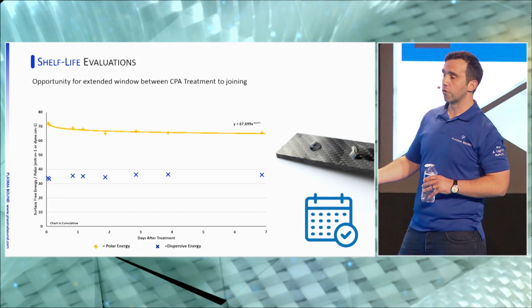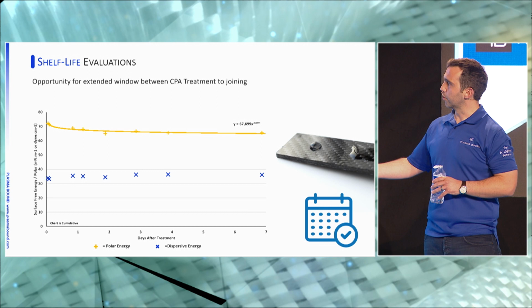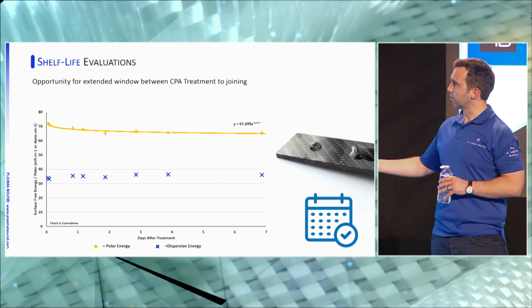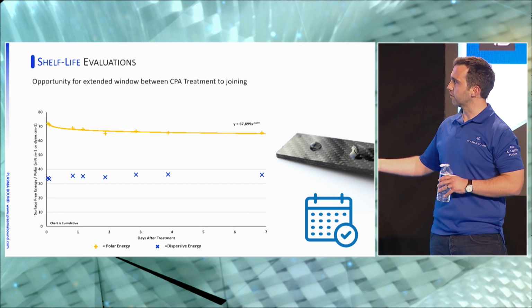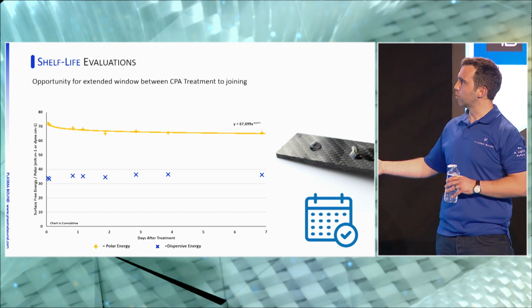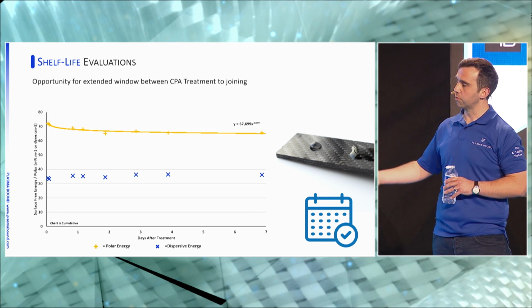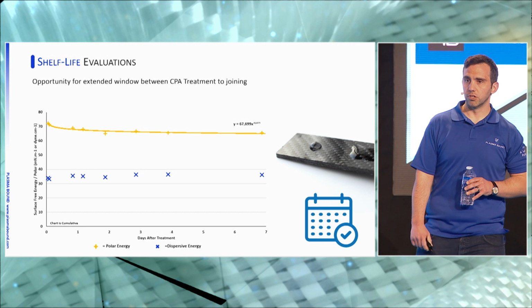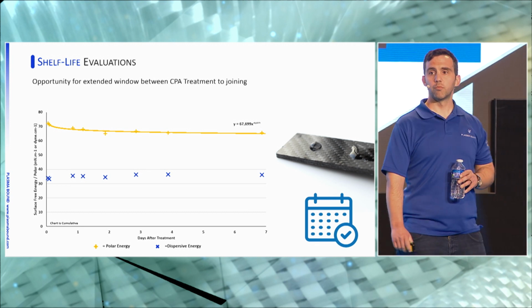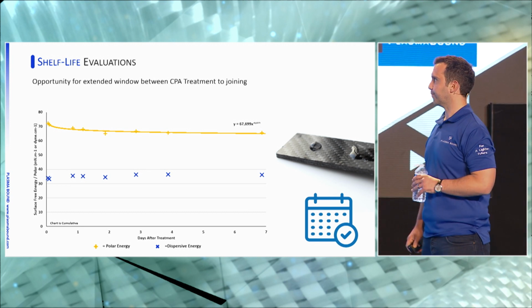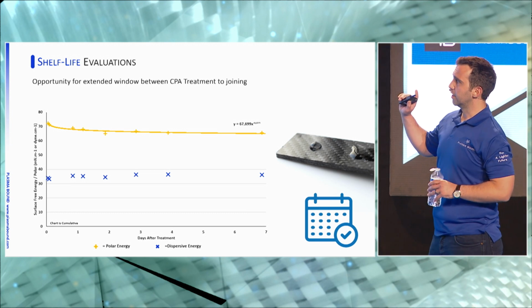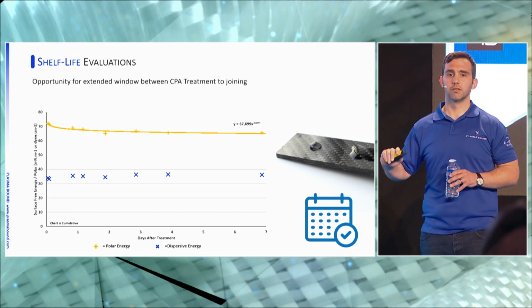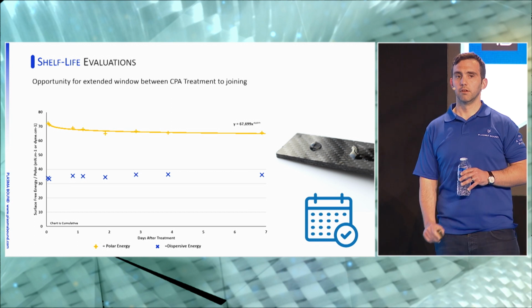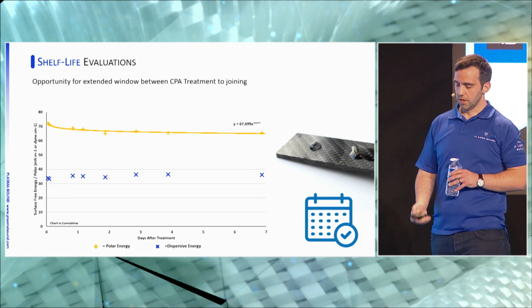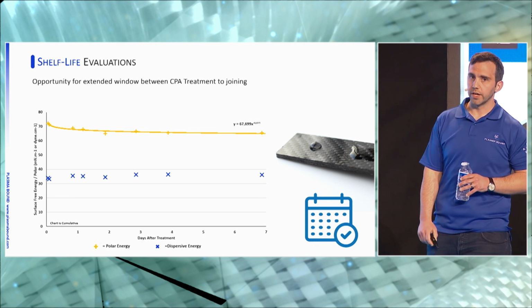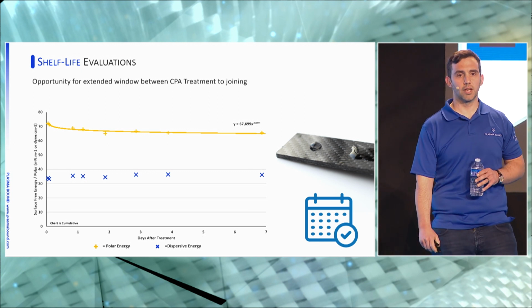And for completeness, and for you all to be able to see, I also demonstrated where the dispersive was. So the dispersive plateaued and remained, and this is what's called polar restoration. Essentially, the polar energy was being satiated by the presence of moisture in the air. So after 7 days, in an uncontrolled environment, that is on a shelf in our lab, those were the results. We have demonstrated that to 22 days for epoxy carbon fiber.